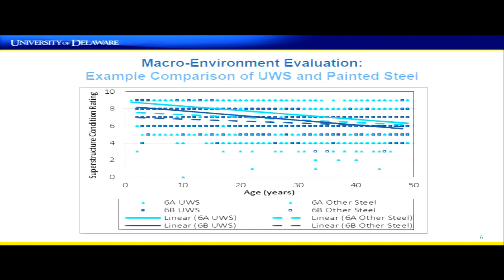But if you apply a trend line to this, the solid lines are the trend lines for weathering steel in 2 agencies, and the dashed lines are the same agency's painted steel. So you see that weathering steel generally is performing better. As we get to older bridges, the trends change a little bit, but again, that's before the modern guidance. The same could be said for paint, though. Those are older paint systems. So for newer bridges, it does seem like weathering steel is performing better than paint based on this data.